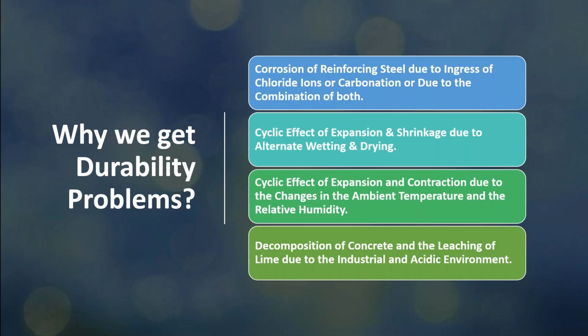The main problems are corrosion of the reinforcing steel due to ingress of chloride ions or carbonation, or due to a combination of both. This is one reason. Another reason is the cyclic effect of expansion and shrinkage due to alternate wetting and drying, cyclic effect of expansion and contraction due to changes in the ambient temperature and relative humidity, and decomposition of the concrete and the leaching of lime due to the industrial and acidic environment. These are some of the durability problems.